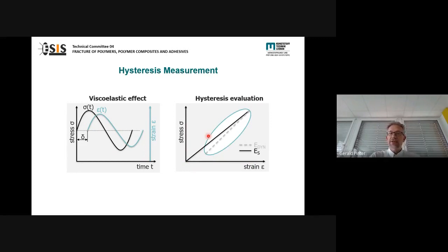And of course, you can measure these hysteresis loops at different cycle numbers and compare them. So looking at that, how can we now define such a hysteresis and the change of the hysteresis? We can typically do this by using two moduli. On the one hand, we can calculate the dynamic modulus, you can see here. And on the other hand, we can calculate the so-called secant modulus, which you can see here, from the origin of the system.